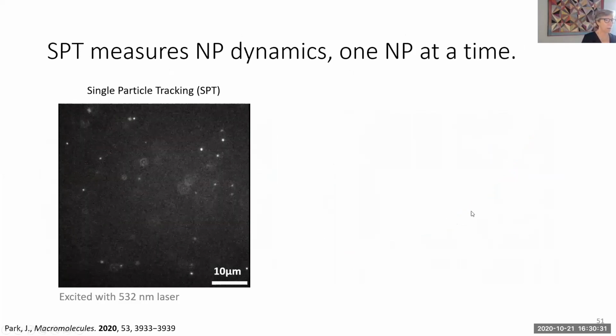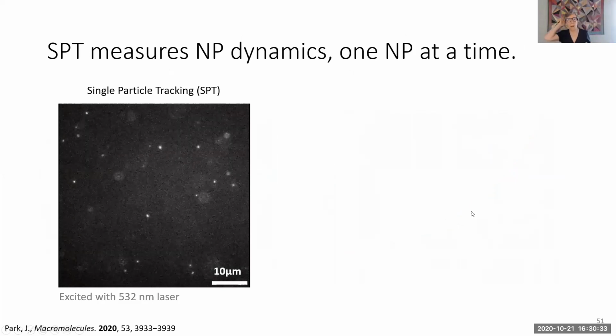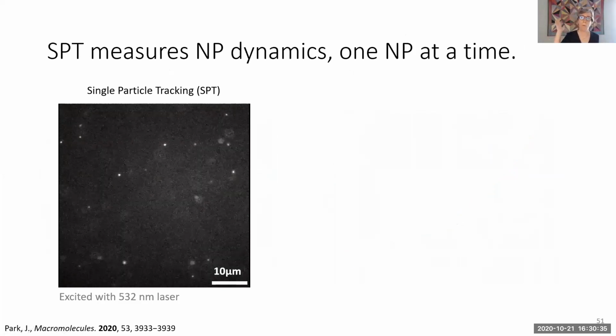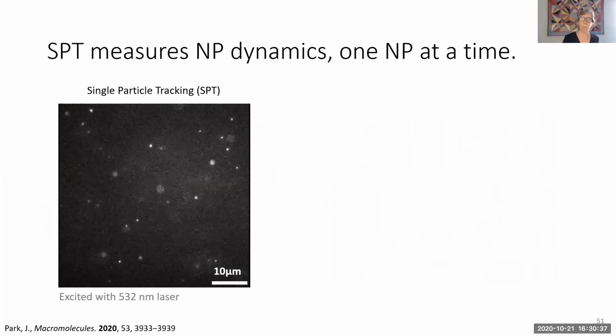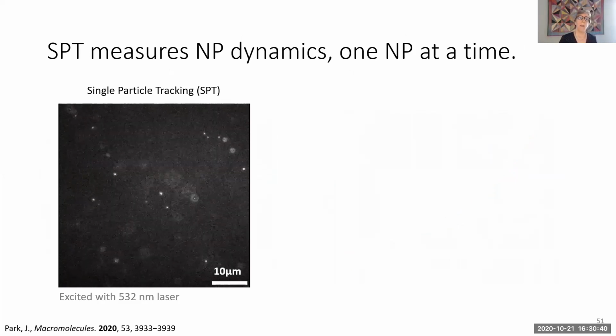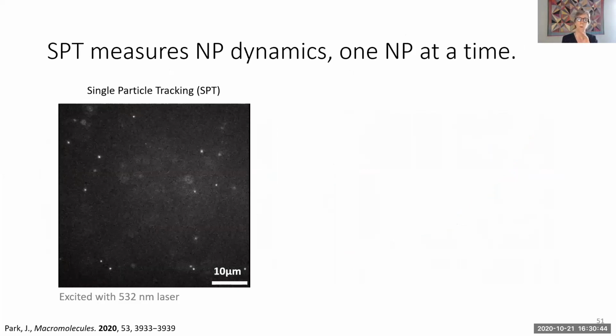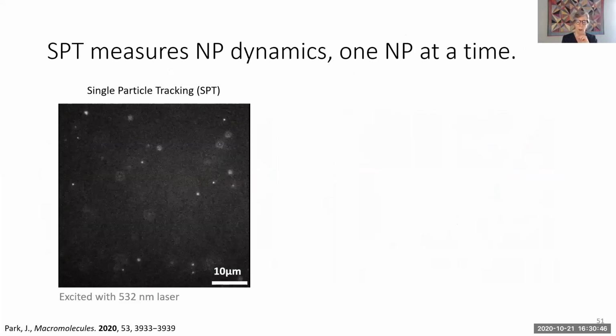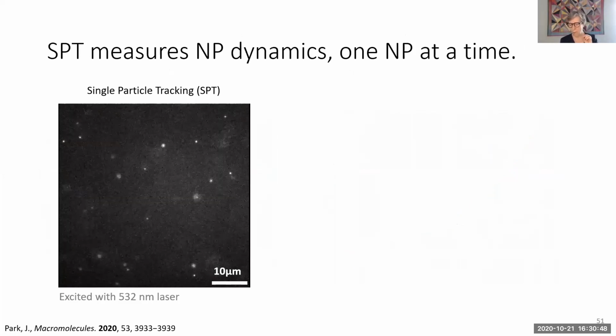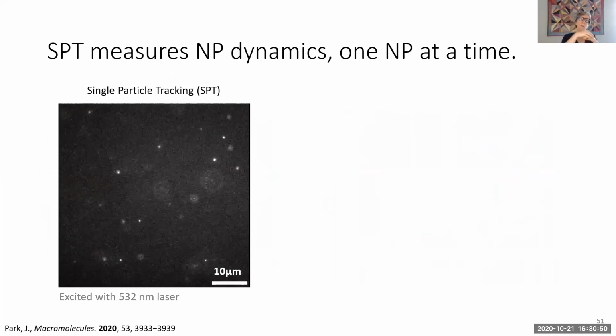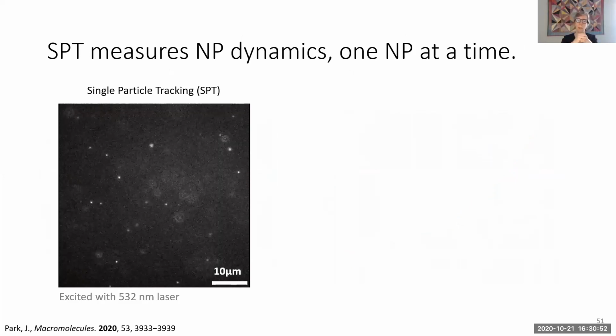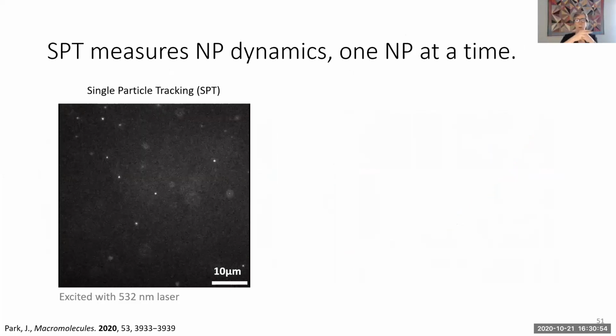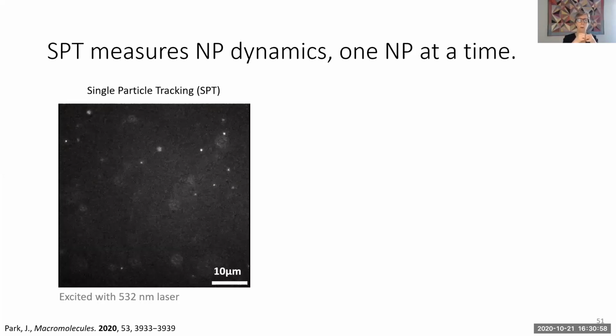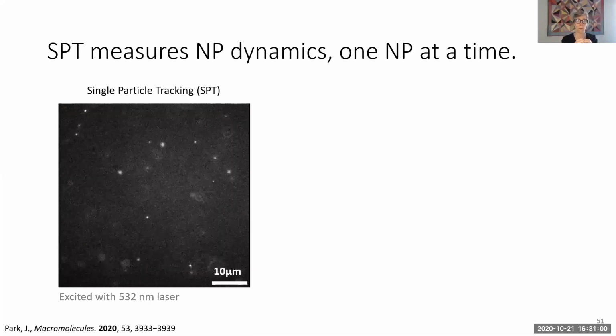Okay, last thing is, I'll just go ahead and start the video so you can watch the little dots move. So single particle tracking is widely used in liquid systems to watch particles move, but we used it to look at a polymer melt. So we went to a new polymer, which was much lower in Tg, because we wanted to look at the effect of this bound layer as a function of particle-polymer interaction. Now, if you have a good, strong interaction, you're going to have a bound layer, and that bound layer is going to prevent particle agglomeration.